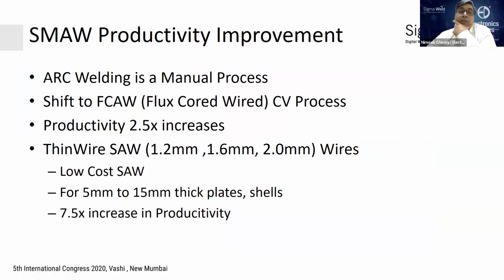SMAW productivity improvement, you can see already we've discussed. From thin wire, your productivity increases 7.5 times, and it's very good for low thickness up to 15 mm plates.